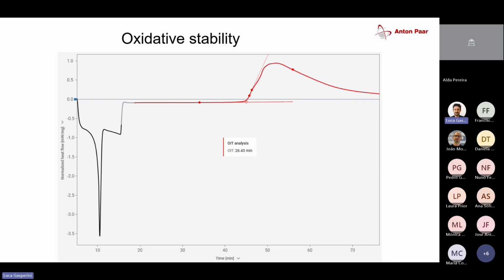However, in most cases, we need the cable insulators to be colored. We need to have a red or black or brown or blue color. So we put a dye or a pigment during the processing. Then we run the OIT analysis again to see if that dye or pigment has affected the oxidation stability of my polyethylene matrix. And I might receive a value, originally I had 26 minutes, that would be 23 minutes. And I might say, okay, so my oxidative stability has decreased a little bit because the oxidation time is shorter, but that might still be enough.